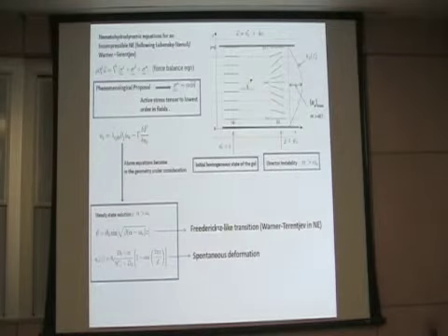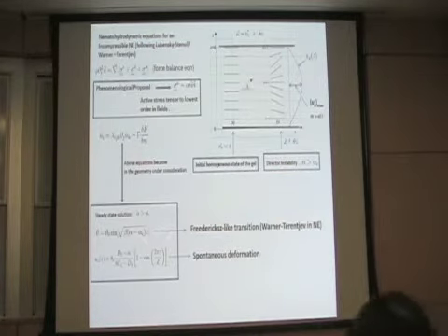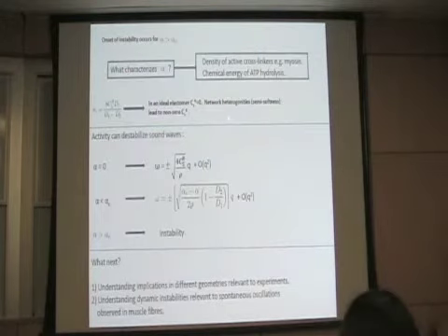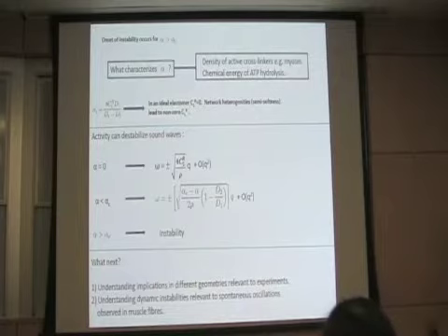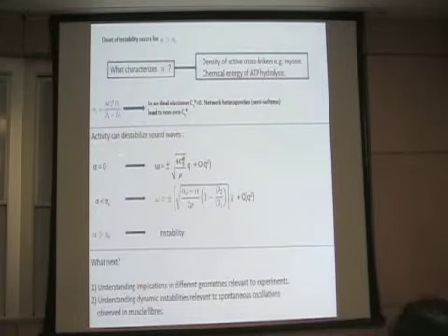One can essentially get various kinds of modes depending on the length of the system. So when activity is tuned beyond the threshold alpha C, which depends on the intrinsic properties of the network, alpha C actually depends on the shear modulus and the coupling constants of the network, and alpha characterizes the density of active crosslinkers. Another way to see this instability is that the activity can destabilize the sound waves.